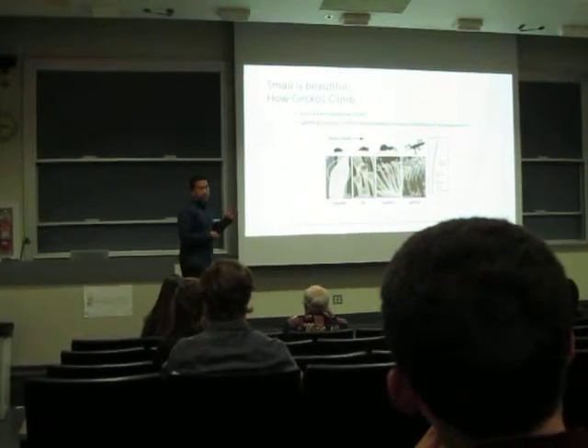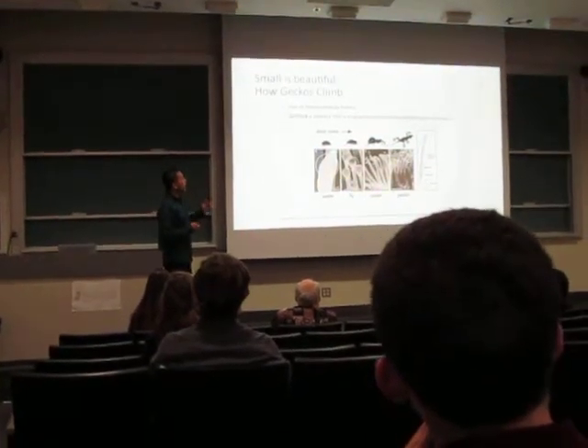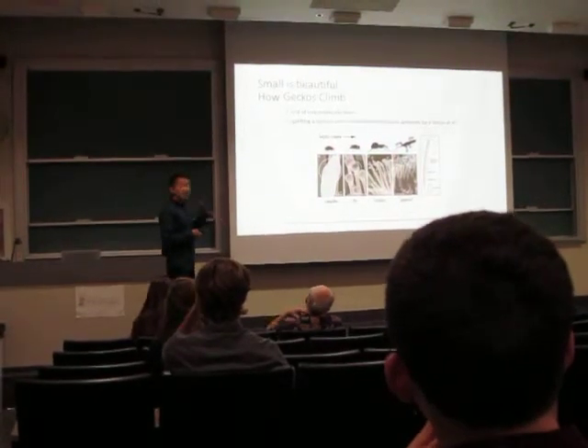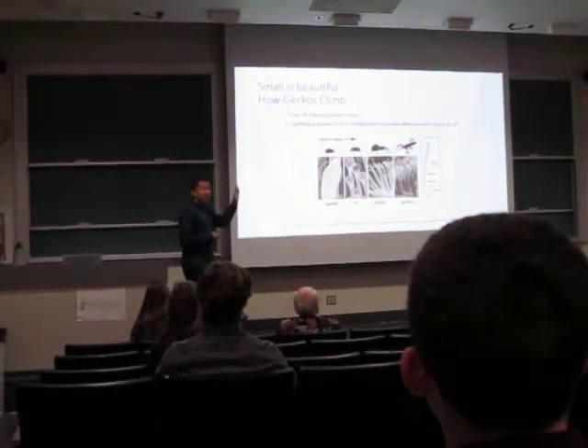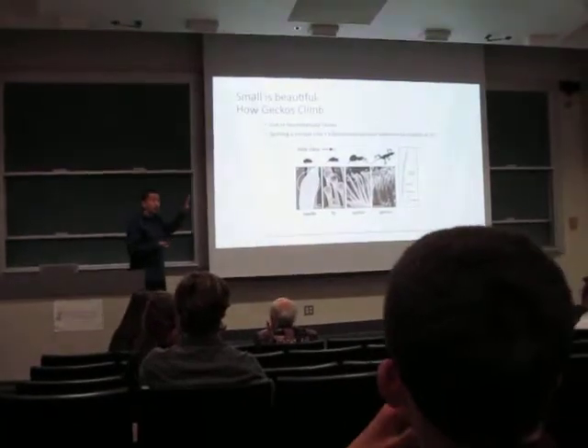Basically, it splits one contact into several contacts, so the adhesion is increased by a factor of n to the 0.5 power, where n is how many pillars there are. If you have one big bump put on the wall, and now you consider so many foot hairs, the adhesion is increased by a tremendous amount.